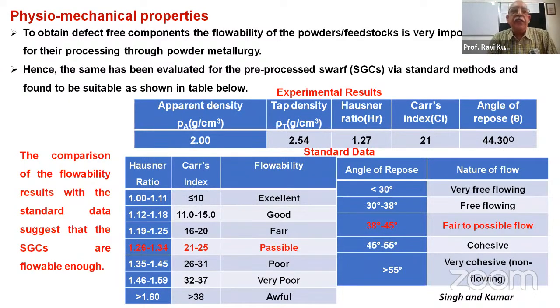To obtain a defect-free component, the powder flowability is a very important parameter of processing through powder metallurgy. What we did, hence, was evaluate it via standard methods, and it was found to be suitable, as shown in the table. We measured the apparent density, then the tap density, then found the Hausner ratio, Carr's index, and angle of repose of the waste particles themselves.